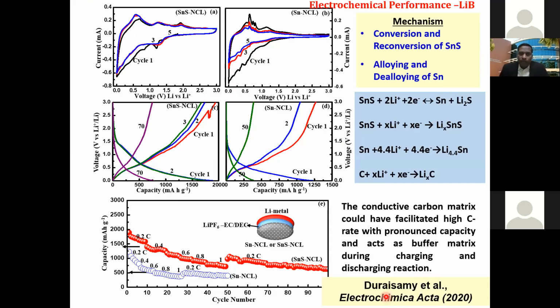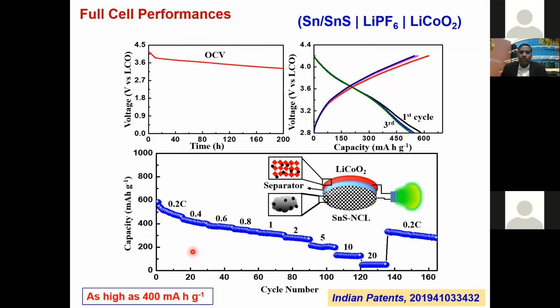What is the half-cell performance? In the half-cell, you use this tin sulfide as an anode and lithium as a counter electrode and do the cyclic voltammetry, which confirms the conversion reaction taking place with the lithium. And this is the discharge capacity. You can get it as high as 500 to 1000 mAh half-cell capacity. What is important is the full cell capacity.